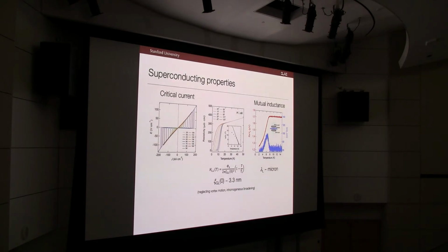And finally, this is a bit strange, right? Nowadays it's pretty common, but in the old days, when I was a student, a requirement for reporting superconductivity was Meissner effects, thermodynamics, or something. I guess in the 2D world, we get a little bit of latitude. But one of the ways we tried to probe some aspects related to this was using mutual inductance. That is to say, we put our thin film sample between 2 coils. We drive an AC magnetic field with 1 coil, and then see what gets through in a pickup coil, and you can see the onset of screening at the superconducting transition.